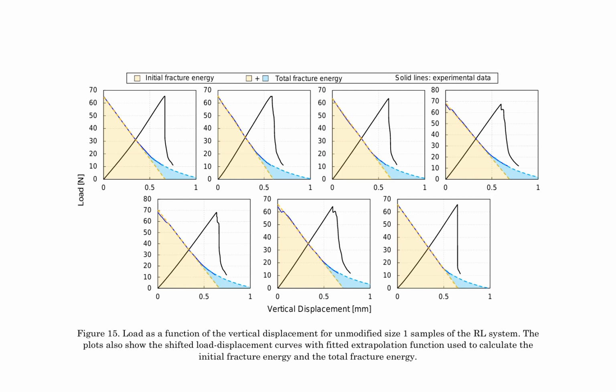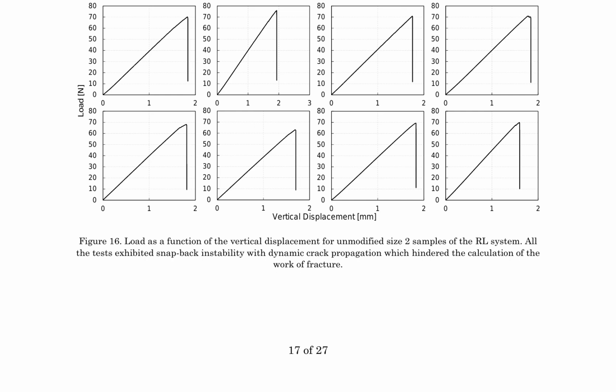In contrast, the size 2 samples in figure 16 exhibited snapback instability with dynamic crack propagation, making it challenging to calculate the work of fracture. This phenomenon is attributed to the sudden release of stored energy during crack propagation, resulting in unstable crack growth. The experimental data, presented as solid lines in both figures, provides valuable insights into the mechanical properties of the RL system. The vertical displacement is measured in millimeters, and the load is measured in newtons. The fitted extrapolation function estimates the initial fracture energy and total fracture energy, critical parameters in understanding the material's mechanical behavior. Notably, the results highlight the importance of considering sample size and material behavior in calculating fracture energy. The findings also underscore the need for careful experimental design and data analysis to accurately determine the material's mechanical properties.